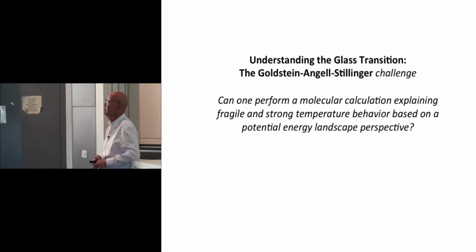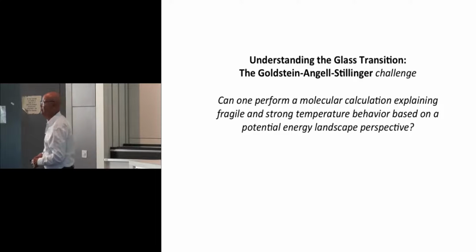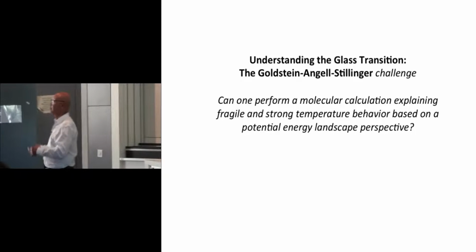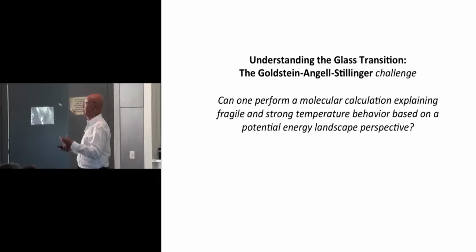Since it's using the same approach, we call that an explanation based on this heuristic approach. The second calculation is for the purist who said, no, we don't necessarily buy transition state theory, but we like linear response theory, Green-Kubo expressions. That's well known in linear response theory, that you can calculate transport coefficients by doing the Green-Kubo formula, which is essentially calculating the stress-stress correlation function, doing its time integral, and getting the shear viscosity.